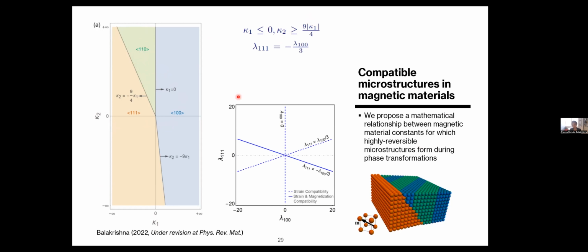And your magnetostriction constant needs to be an interplay between the two constants over here. So all of this calculation was done using a cubic lattice symmetry as the reference paramagnetic phase. And so your magnetostriction constants need to satisfy this delicate balance where lambda 111 is a negative of a third of the magnetostriction and the other constant. So for these values, we expect the material to form a stress-free interface.